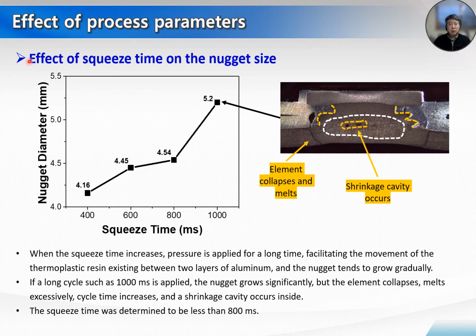This is the effect of squeeze time on nugget size. The squeeze time is the time before the main welding current or preheating current is applied. So when squeeze time increases, pressure is applied for a long time, which facilitates the movement of the thermoplastic resin existing between two layers of the aluminum. The nugget tends to grow gradually.